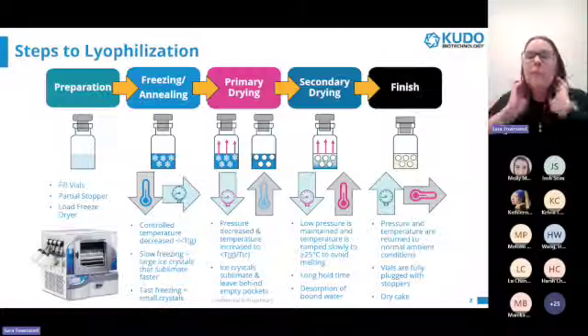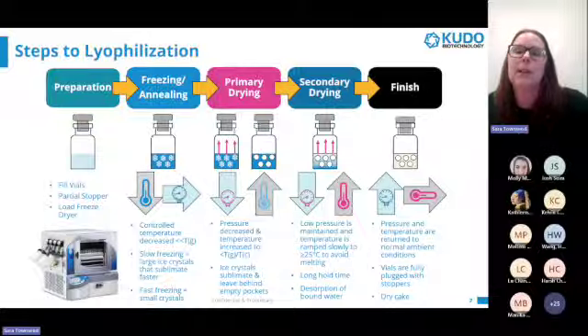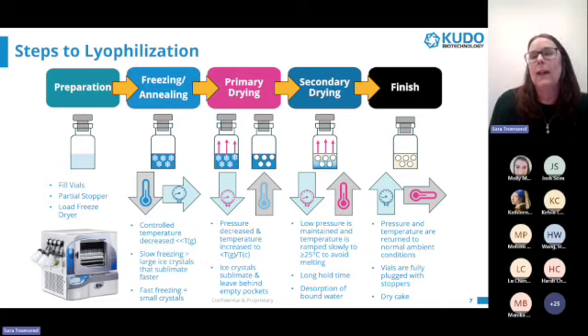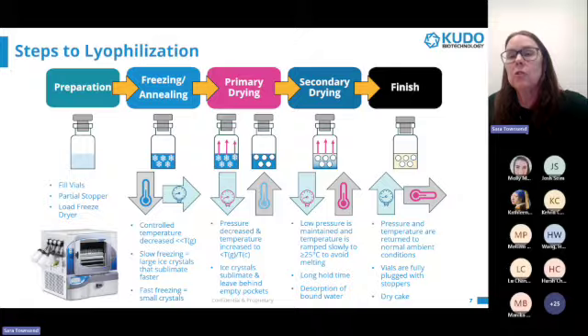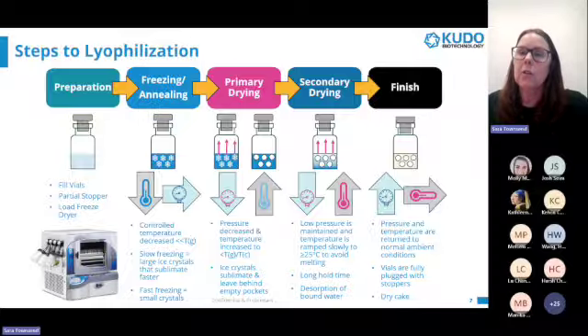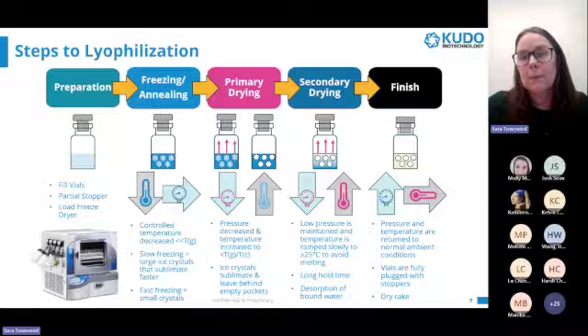There are 5 main steps in the freeze drying process. After the LNPs are formulated into their buffer plus their cryoprotectants, they are filled into vials. The vials are partially stoppered and then loaded onto shelves in the freeze dryer. A partial stopper ensures that the water vapors can escape out of the top of the vial instead of being trapped inside to rehydrate the material.